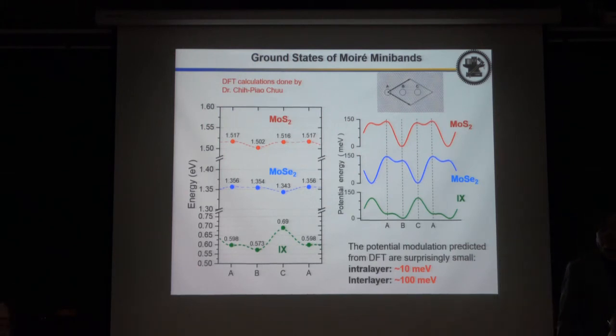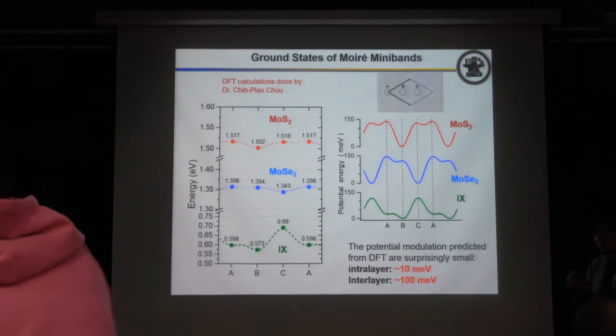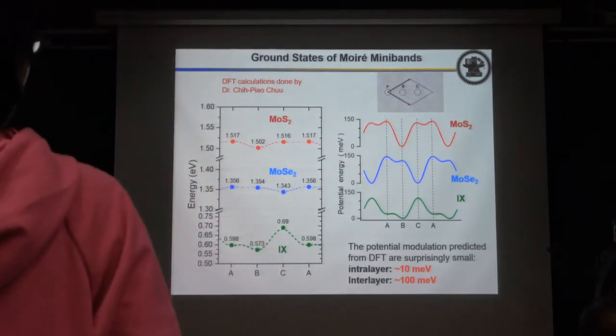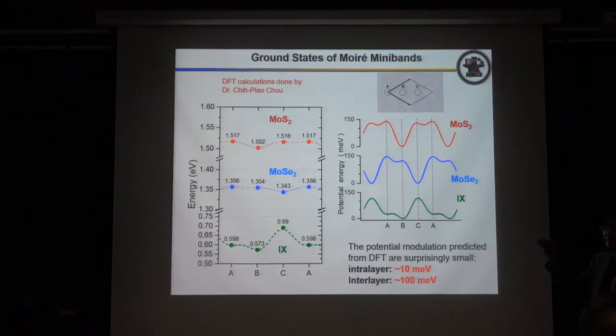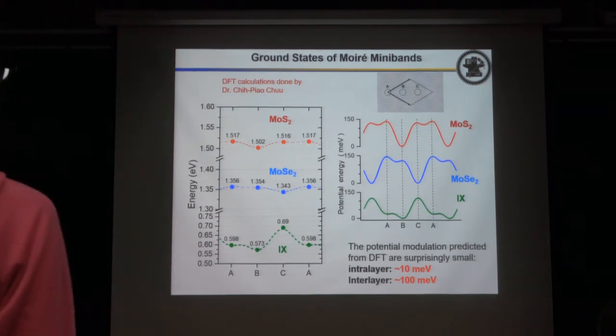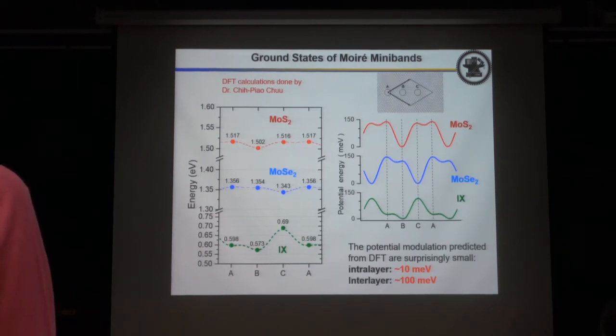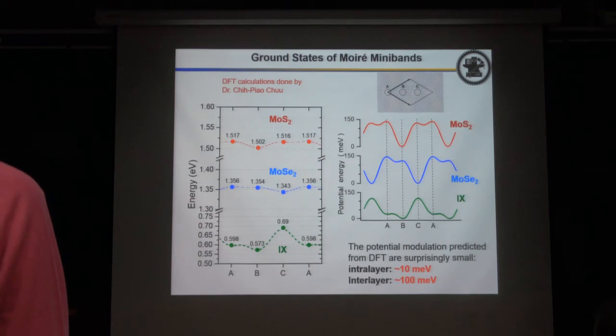Actually, you already made a very short remark on the strain effect in all the heterostructures, no matter what. Yes, due to the fundamental lattice mismatch. Another thing is that perhaps the thermal expansion mismatch is also contributing. Yes, thermal mismatch will occur, especially since we use a very high growth temperature, especially on sapphire or oxide. But for metal, because our growth temperature is quite high, approaching the melting point, I'm not sure, but maybe the mismatch is not a very important problem.